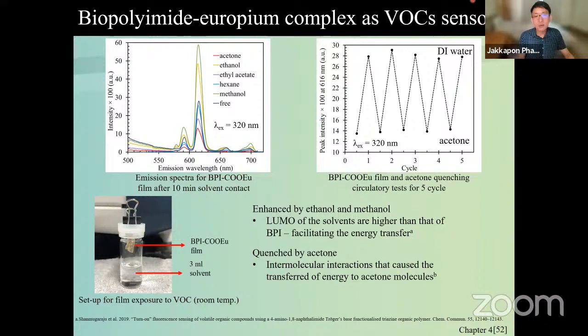You will see that when it has acetone, the brightness goes down. And when I wash it with DI water and do the same test again, the brightness goes up. You see that this can be used as a sensor. If there is acetone, the brightness goes down. If there is no acetone, the brightness goes up.